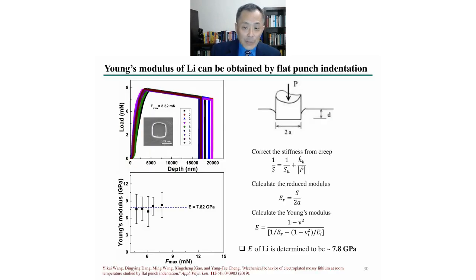However, with flat punch indentation, we were able to obtain the modulus of metallic lithium. Here we use a fairly large size indenter, and then we load, hold, and unload using these equations proposed, well known in the community. We were able to determine the modulus of metallic lithium, which is about 7.8 gigapascals.